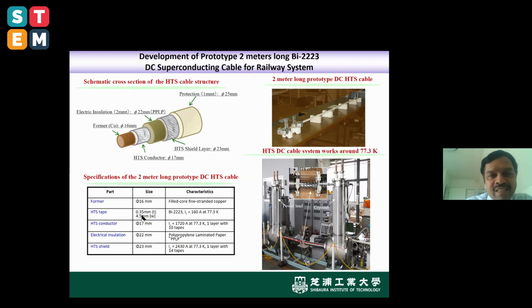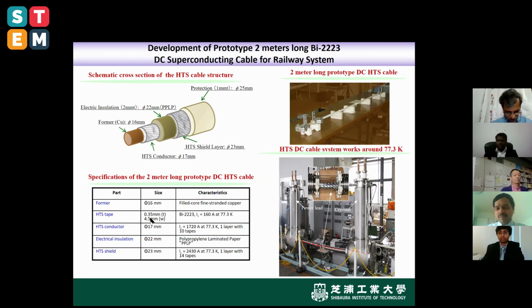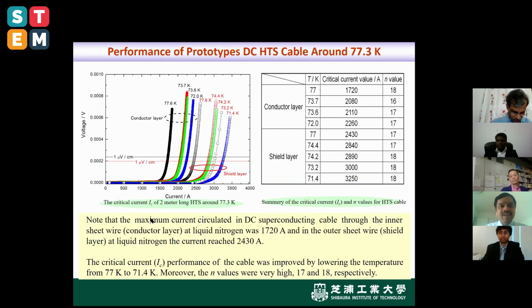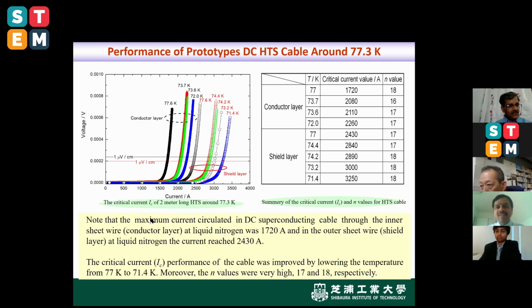What we used here is the 2-meter cable length. Then a locally made cryostat was developed to cool this 2-meter cable, and we tested the current characteristics. You can see the conductor layer and the shielding layer. The conductor layer we normally use as the positive terminal and the shielding layer as the negative terminal. For these two superconducting layers, you can see 1720 A to 3250 A. These results clearly indicate that one can use DC cables for the system.